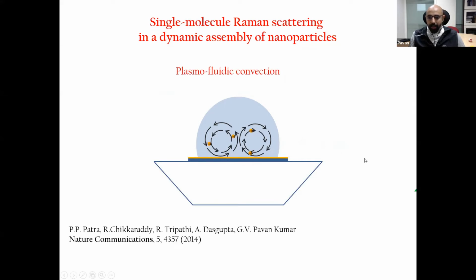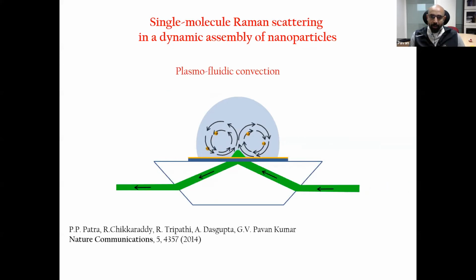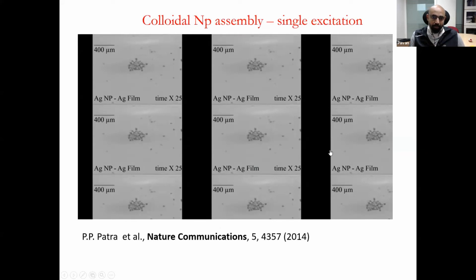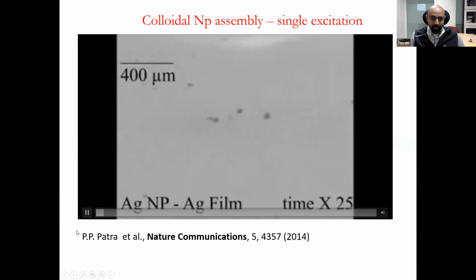On top of that is a droplet which contains gold or silver or any kind of nanoparticle of interest. And now we illuminate this surface. We excite the plasmon, and this creates an optothermal field at the location of interest. The particles get arrested and trapped in this particular structure. So let me show you a video of this kind of structure. What you end up getting is these kinds of assembly processes.